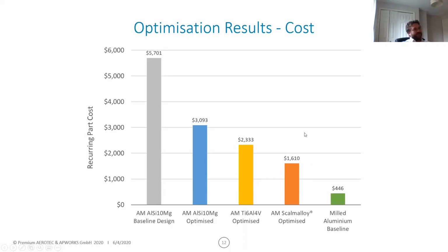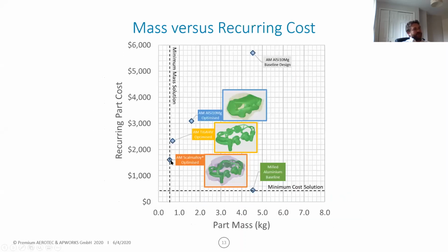But maybe you value weight saving enough, because weight saving is what you get in combination. So this Pareto front, just to understand, you have the part cost on this axis and the part mass on this axis. And this is the baseline. So the baseline milled part represents the minimum cost solution. The interesting thing here is, typically with machining, if you were to optimize the part for mass, but stick with machining, you would normally see that as you reduce the mass, the price would go up. So you would have a line in this orientation.